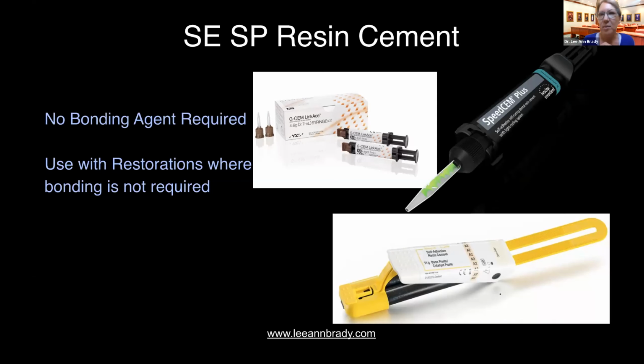The other thing that I want to mention about that is I also said to go back and cover all the margins with glycerin or deox. Every resin-based material has some amount of an air inhibited layer. The thickness of that air or oxygen inhibited layer depends upon filler percentage and chemistry, and there's all sorts of science, okay? But they all have them. And when you're talking about resin-based cements, that oxygen inhibited layer could be as much as 50 microns. If you are not curing every version of a resin-based cement under an oxygen barrier, you could be leaving a 50 micron layer that never polymerizes.